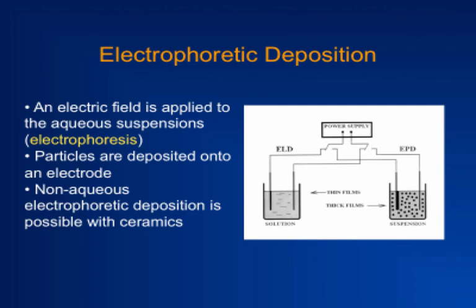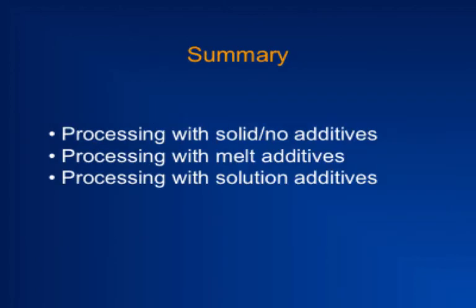So as you go to nano, inkjet printing and electrophoretic deposition are all different kinds of solution processing that take advantage of small particle size and low concentration, right? Because synthesis methods typically will have a suspension that is created, if you know how to create it with fine dispersion, without agglomerates. You don't want to dry out the powder and form agglomerates again and then redisperse them. You want to use it directly as a suspension, whether it's a Stöber synthesis or the like. So now the idea of using suspensions, polymer solutions that are holding dispersed particles, becomes more and more important when you're trying to deal with creating shapes out of nanoparticles. Okay. So that's my summary.